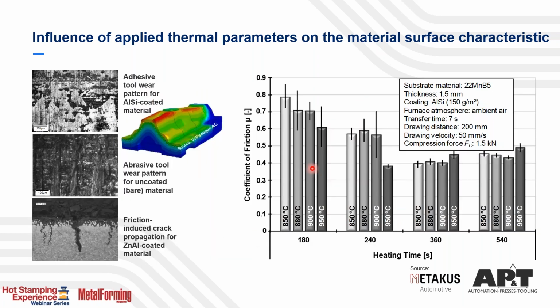In the next page, we see the influence of different heating times and different final temperatures on the coefficient of friction. And that is very important to understand the influence of the coefficient of friction in the press hardening process, especially when thinking about die wear. High roughness is, of course, leading to adhesive and or more abrasive tool wear. And this is, of course, something we would like to avoid. So you would need to find a temperature time setting, which gives you the best results in terms of the coefficient of friction. So we're somewhere here in this area here, where you then can manage to have less abrasive die wear, and you don't need to maintain your dies that often.